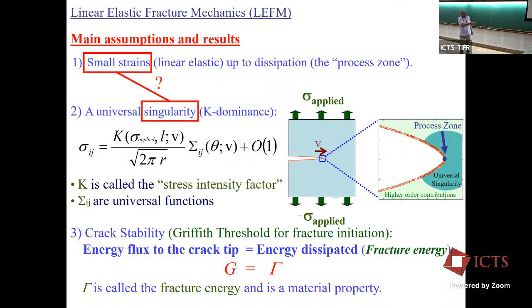And far enough away from the crack, this small strain is fine because you're not pulling anywhere near the theoretical strength of the material. So the strains are small. The contradiction comes in the region where you're actually breaking things at the tip of the crack, because there you're stretching things enough in order to break the material. So you can't really assume that the material is linear elastic because you're breaking it. So that's where the contradiction lies. Any other questions?